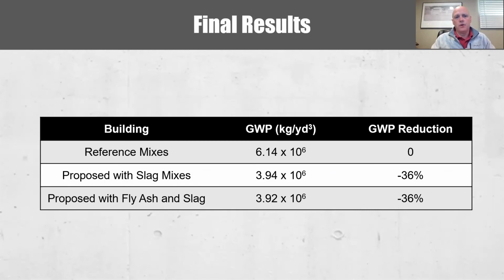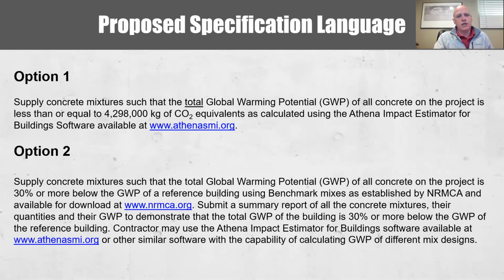And here are the results. So the reference mixes, call that the reference, or 0 point. The proposed slag mixes would reduce the carbon footprint by 36%, and the fly ash and slag mixes by a similar amount. So how would you specify this? We suggest two options. One, actually give a target carbon footprint that a contractor and concrete producer needs to meet, and they can do the calculation to demonstrate that they met that.